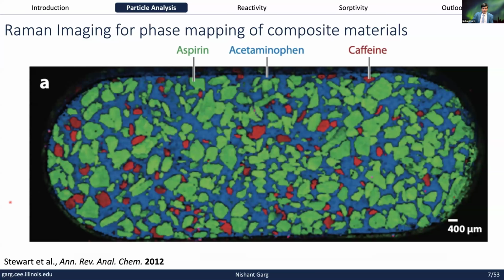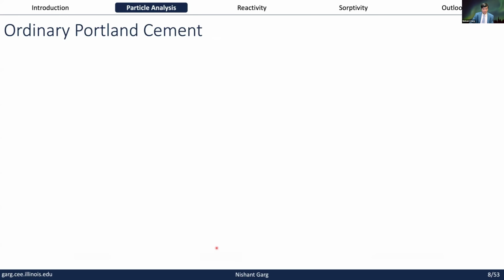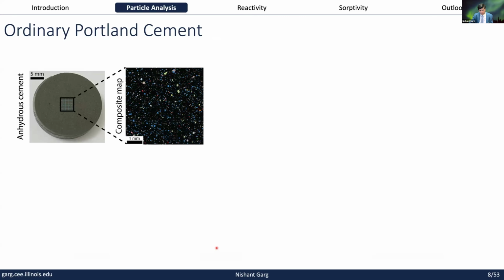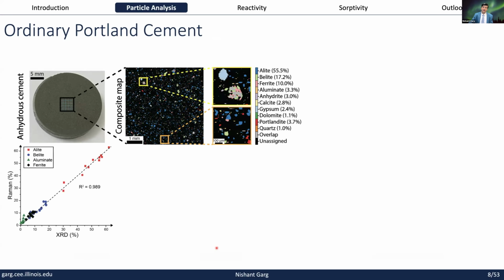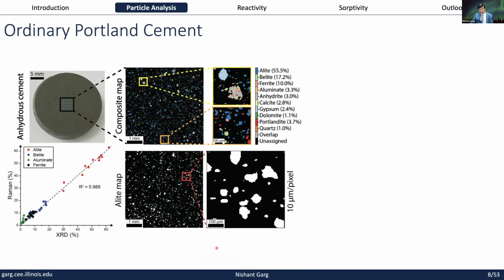And what we find out here, let me give a second. We made these little pills of ordinary Portland cement, where we are able to quantify almost all the phases that are present in it. These are largely crystalline. When we compare the quantification with gold standard techniques such as X-ray diffraction, we get a decent correlation. And the nice thing with Raman is that now you can start to see individual grains of these minerals at a very, very high resolution, right?